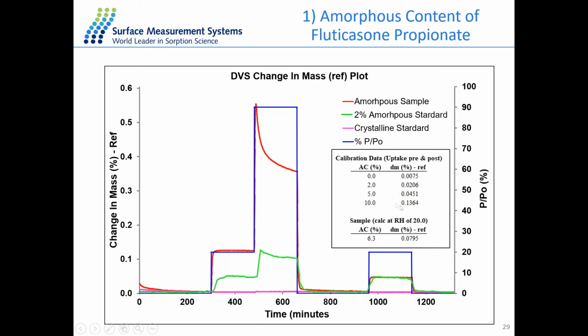So we have the mass change of this crystalline material or the amorphous standard, and then we have the mass change for the sample of interest. So we have the calibration line from the standard material, and we fit this point onto the line, then we can get the amorphous content of the material of interest. So it's quite a simple experiment as long as we can find a solvent that will induce the crystallization and a standard of the same nature as the material.